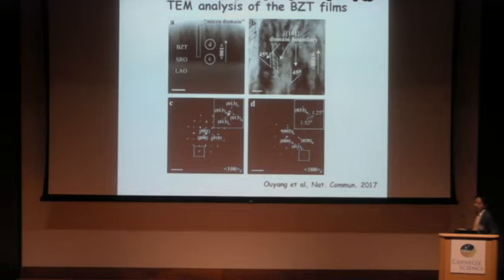And we did some very intensive TEM work. We checked four different thicknesses: 350, 700, 1.4 micrometer. The thickest is 1.8. Here I'm showing you just an example. This film is about 700. This is 200, the scale bar is 200, so this is about 700 nanometer. You can see all these column-like structures. And then when you zoom in, you can see all this nicely oriented zigzag kind of domain structure at 45 degrees with respect to the growth direction. So by just looking at the crystallography, you can tell all these are the higher order domain structure of rhombohedral.